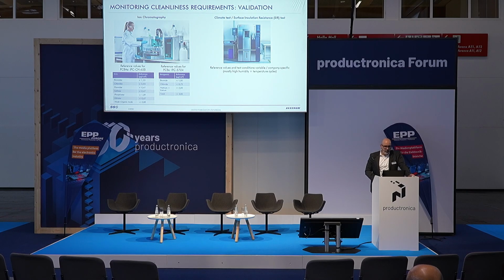And as I already mentioned, during the validation you can use ion chromatography, where you really get the information on the different ions, which again gives you an indication of where a contamination comes from. So depending on your solder paste or flux that you have on the PCBAs or other materials, you get an indication of what's actually the issue, what you have to remove. And the SIR test is also a test which is used for the qualification of a process, especially of a coating process, where you have a comb structure and then apply the coating and put the test structure in a climate chamber, and then you can see if there's an increased leakage current. And once you pass this test, you know, okay, the process is fine. So this is again part of the validation.